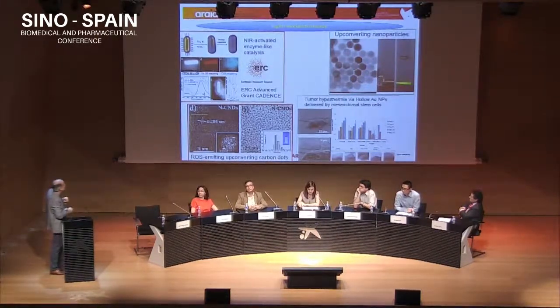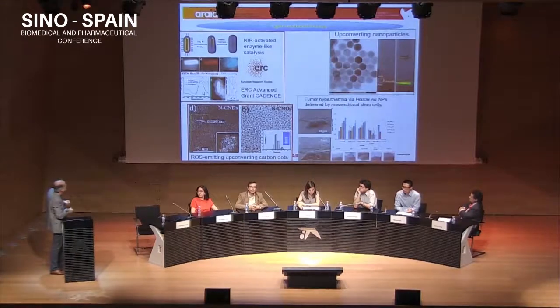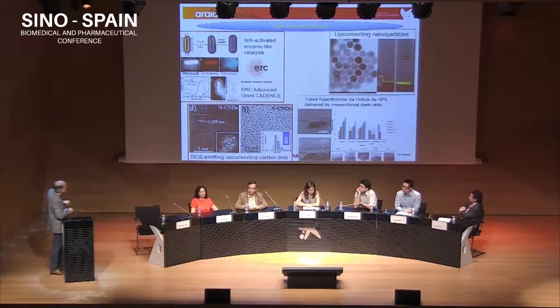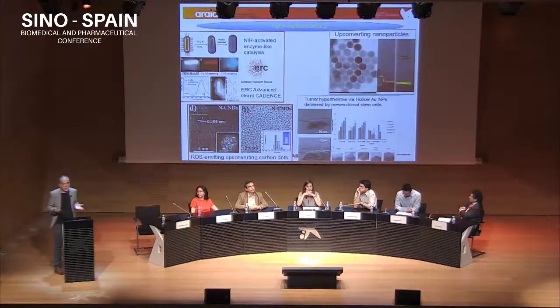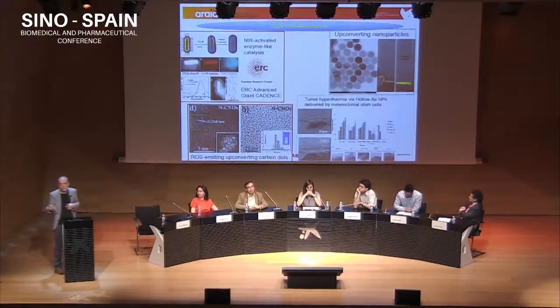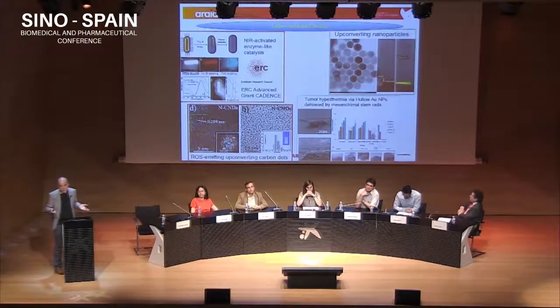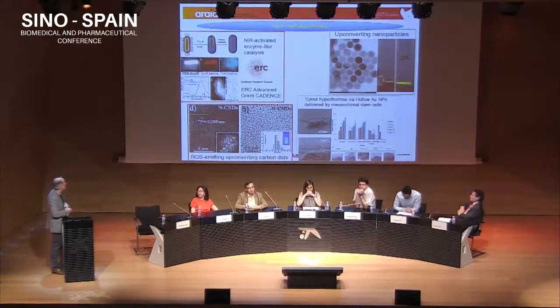And now these electrons, the hot electrons, are being passed to the titanium coating, okay? And this hybrid nanoparticle, the gold nanorod plus the titanium coating, is able to act as a hydrogen peroxidase enzyme without the limitations of pH or temperature that the natural enzymes do have.